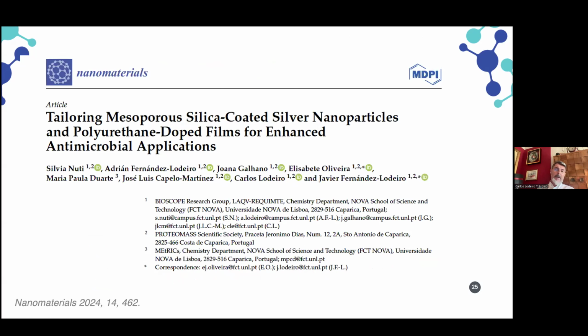And if you go to practical applications, we need to encapsulate the nanoparticles or entrap the nanoparticles in other materials that are easily handled. And in this case, we are working with different polymers and copolymers. The results I show you here were using a polyurethane, Irogran, in which we introduce the nanoparticles with the mesoporous silica in order to use these flexible materials as antimicrobial tools. For example, if you like to cover a table, or in a hospital you like to prevent contamination in a surgical block, you can use these coated polymers in order to eliminate completely the growth of the bacteria.